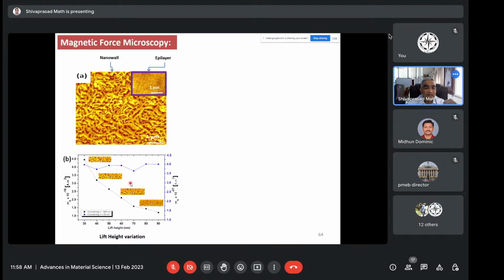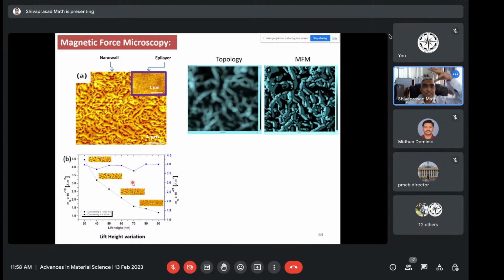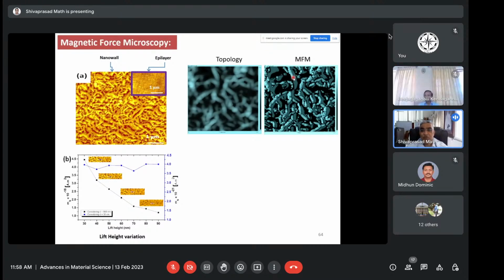So we showed that, and then to prove that there's actually true magnetism, I did another experiment at Northwestern University, where they had a facility where they could change the external magnetic field outside the MFM. And when I did that, I could see that the tips of the walls of my nanowalls were purely magnetic with a very good high resolution magnetic force microscope.